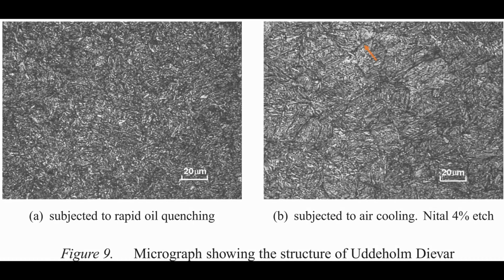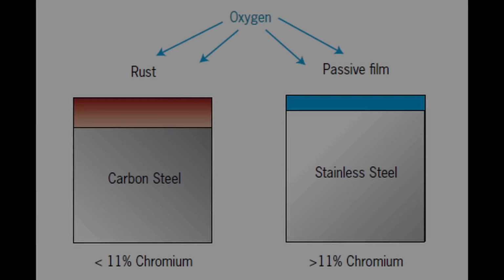So corrosion resistance, I'm just going to hit on briefly. Again, the carbides precipitated during a slow quench are the thing that is most detrimental to corrosion resistance when it comes to the equipment that we are using. Those carbides precipitate out, and they are chromium carbides typically. So it's taking chromium from the matrix of the steel, and you need that chromium in the matrix so that at the surface it can form the chromium oxide. That's what makes stainless steels stainless. You get free chromium at the surface, and that forms with oxygen to make a protective chromium oxide layer on the surface.